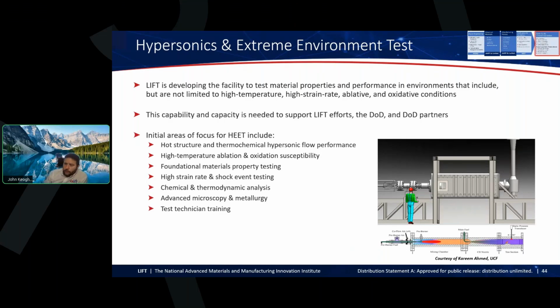But we're building with Kareem at UCF a larger version of this test chamber at LIFT, as I mentioned earlier. I already really gave you the figures in there: Mach 4 through 8, up to roughly 3,500 Kelvin stagnation, 170 atmospheres stagnation pressure, and it's effectively a continuous runtime compared to, say, shock tunnels and things like that, where you get 10 to maybe 20 milliseconds of data. So, pardon me, that will be online mid-2027.